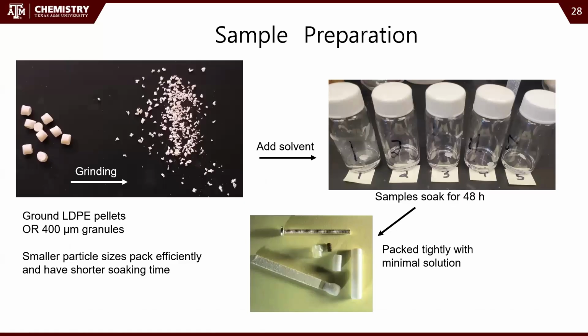Okay, so we started with just LDPE pellets and 400 micron LDPE granules. We tried them both. We just ground up the pellets into nice small granules, and they didn't really make a difference. Then we soaked them in solvent for a good long while to get them nice and fully saturated. And then we packed them in this HR MAS rotor with kind of the minimum solution that we can get, so that we have as few solvent signals as we can get. We have a big signal just from the LDPE.